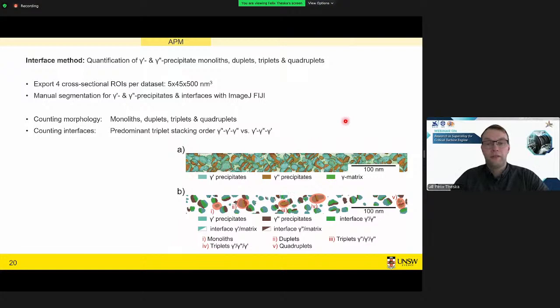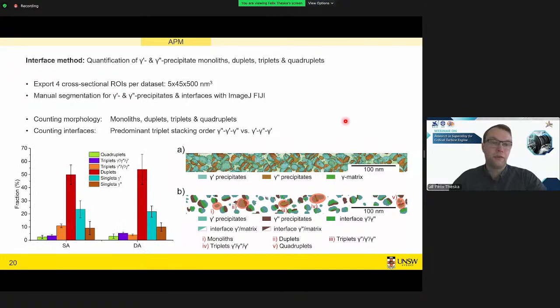Once we've done this, we can start counting what are single particles or monoliths, what are duplet particles where two sit together, what are triplet particles or even quadruplet particles. And once we're done with this counting, we can compare them. You see in these different colors, we have these different morphologies sitting together. And what we have observed before is basically represented here again, where SA represents our conventional processing, where we have much more of these triplets with gamma prime as the center, and DA, after direct aging, we actually do have more triplets with gamma double prime in the center.